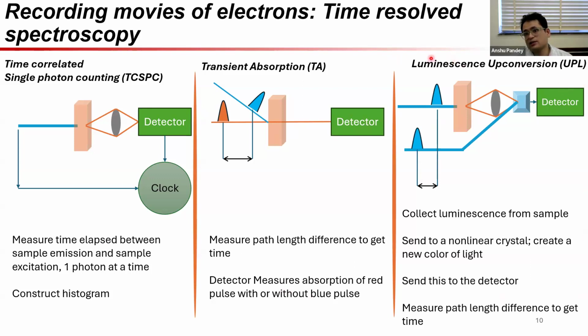The third technique which we'll invoke is luminescence upconversion, or UPL. This seems at first blush just like time correlated single photon counting. There's one obvious difference and one very subtle difference, and I'll get to the subtle one as we go along. How this technique works is that it again uses the idea of measuring path length difference between pulses to measure time. You have a powerful pulse hitting the sample. This causes the sample to get excited. Meanwhile, a second pulse, which is arriving at different points of time, is directed onto this nonlinear crystal. The sample's emission is also directed onto this crystal. At a very precise point of time, when both the sample's emission and this particular pulse arrive at the same time, the light from this crystal is amplified and this new color is sent to the detector. So we are not measuring the emission directly, but rather only the new color of light, which is produced by the sum of this pulse and the emission coming from the sample.